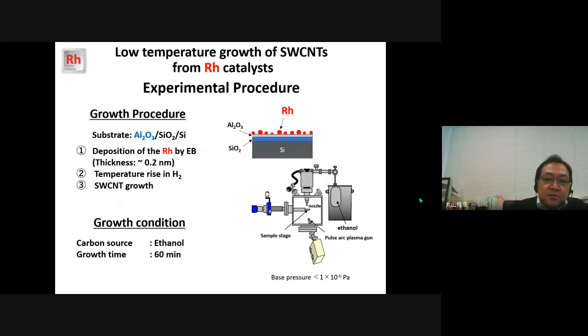Here, we use rhodium as catalyst to perform low temperature growth. Rhodium catalysts were deposited on Al2O3 SiO2 silicon substrate. Then SWCNT growth was performed by ACCVD. Next, please.